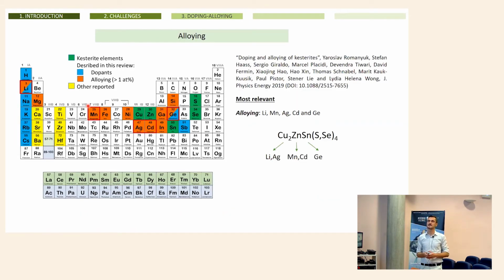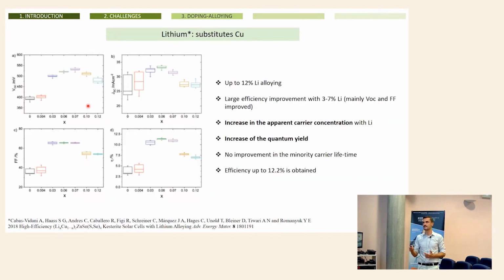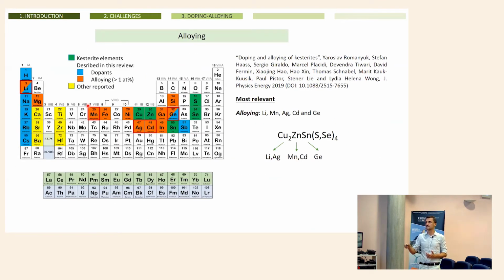To go faster, now I will jump to alloying, because another possibility is to change the material drastically, not just with doping where you are adding tiny quantities of material. Here we will change the material drastically, substituting large quantities of each element in your structure. This is the basic structure of kesterite: copper, zinc, tin, sulfur, selenium. And then you can substitute copper by lithium and silver, zinc by manganese and cadmium, tin by germanium. And these are the main elements that have been investigated.